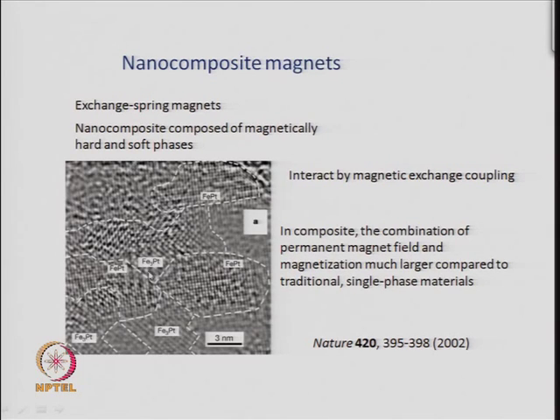Whereas this part, you can see, has a different kind of contrast and different kind of lattice fringes. The lines you are seeing here are called lattice fringes, and they tell you about the crystal structure, the difference in the atomic planes in the material. So, from that we can identify that this is iron platinum, one from the lattice fringes, and second by doing energy dispersive X-ray analysis on this part of the sample, you can find out that this is iron platinum 1:1, and this part is iron platinum 3:1 ratio. And they are two different types of materials.